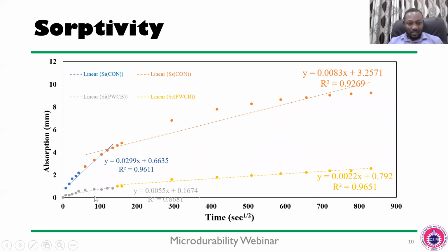So with the sorptivity test, we look at the capillary action. At the primary sorptivity, this is what we are having. For the control, this is the control line, and then the one that is containing the waste clay brick. Of course, we can see that that one was very much lower. So we have a gradient of 0.0055 compared to that of 0.0299. Which means that the one containing the waste clay brick has the ability to resist the ingress of harmful ions. It was the same for the secondary sorptivity. We have the one with the waste clay brick at 0.0022 compared to this one, which was 0.0083. So it can be concluded that this is much lower than the control.